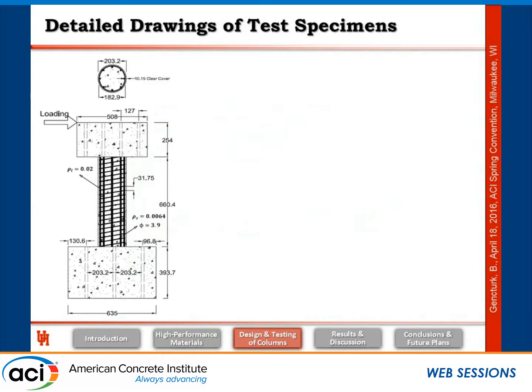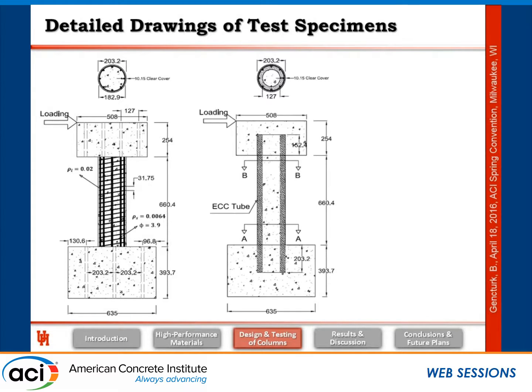Now I would like to start talking about these columns. So these are the columns that we built and tested. These are 8-inch diameter columns, and they have about 2% longitudinal reinforcement, about 0.6% transverse reinforcement. The aspect ratio is 4.5, so the loading point is about 36 inches from the base. These are pretty small columns. You will see some pictures later on. So this was the conventional reinforced concrete column. This is the ECC tube. So you see on the outside we have ECC.